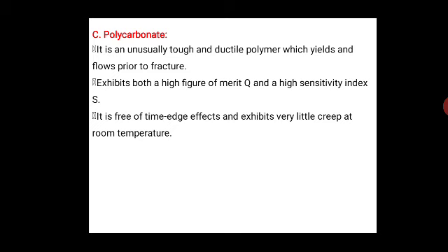Polycarbonate material is also difficult to machine. Any significant heat produced by the cutting tool will cause the material to soften and deform under the tool. The best method of machining is routing, which can be performed only under water, and sawing and milling are practically impossible.